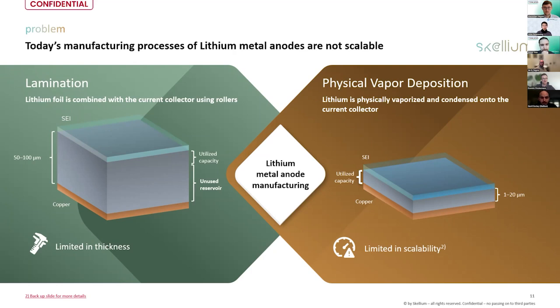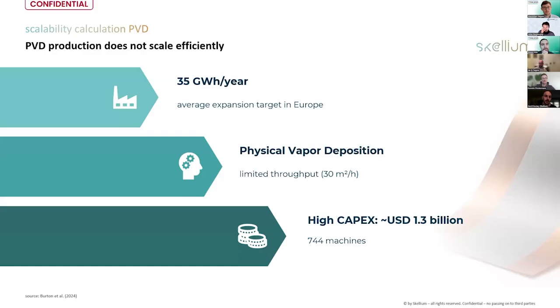And on the other hand, you have the lithium metal which is deposited by vapor. You can imagine that vapor deposition is very, very slow, so it's also limited in scalability. Scalability is most of the time a buzzword that everybody just throws into the room, and nobody asks about it. But what does this actually mean? When we look into a 35 gigawatt-hour European production plant, which was more or less the standard production target for Europe for 2030, with average physical vapor deposition equipment you need 744 machines for producing the lithium metal electrodes, which is around 1.3 billion of capex. So therefore, I would say we can put a tick behind it that PVD processes are not that scalable.